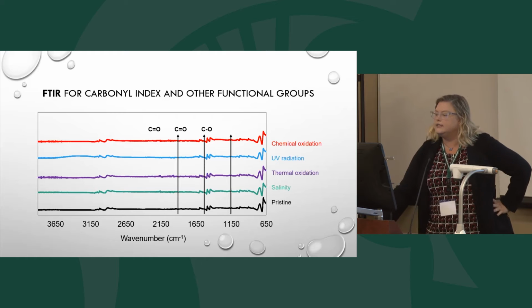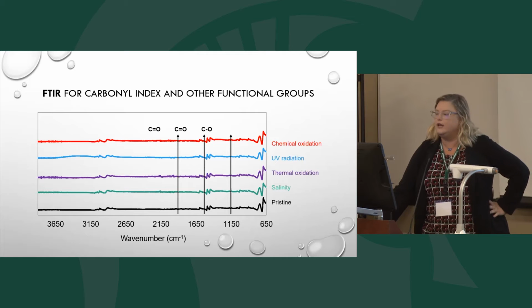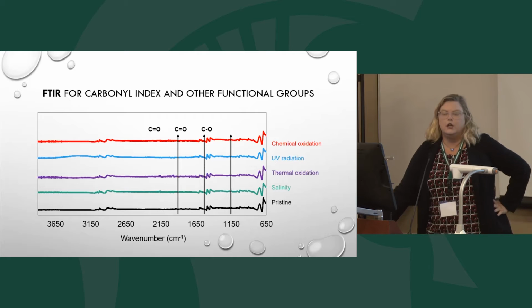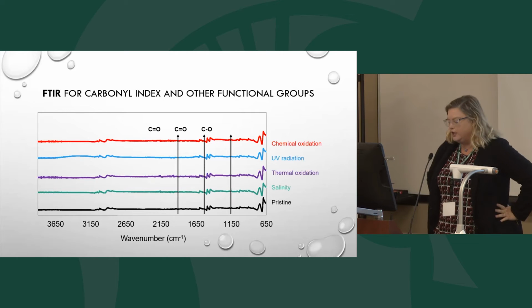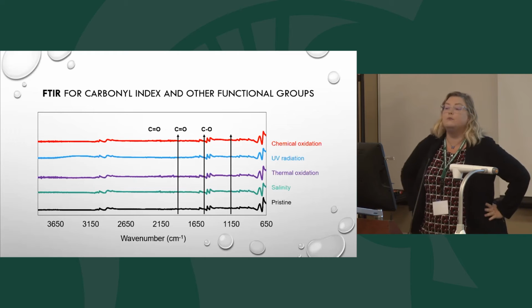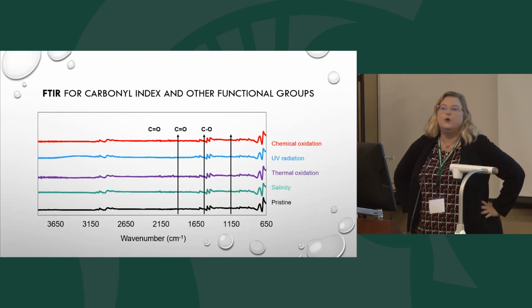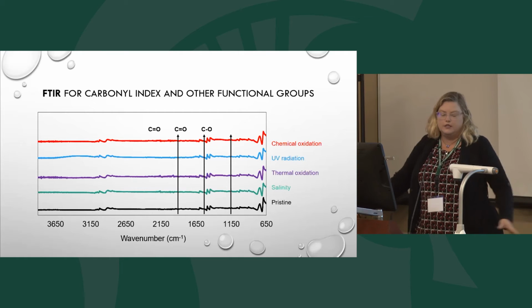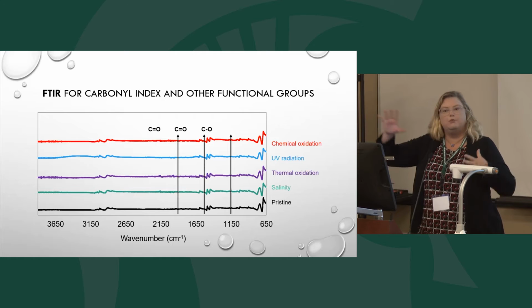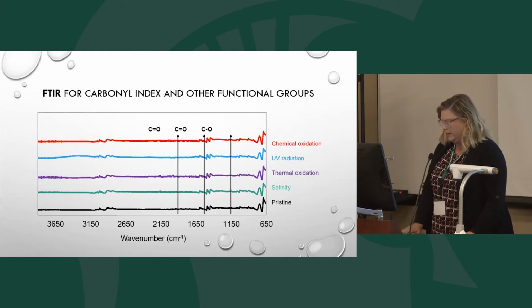You can see, this is only where the microplastics were in the environmental chamber for 2 weeks, we saw virtually no changes in the carbonyl index after the microplastics were exposed to each one of these particular things for only a 2-week duration. So when we're looking at the accelerated aging, we have to think long and hard about this and do a lot more studies to see how long we will have to keep the particles in an accelerated aging weathering situation and see how that matches up with the weathering that is existing in real life microplastics coming from the beaches and other waterways and other sources.